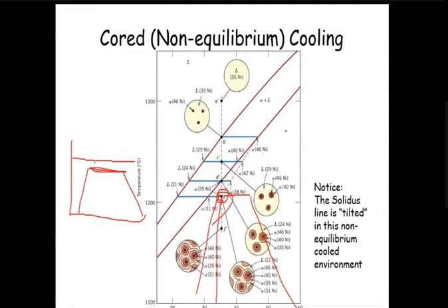So why is this holding important? Because due to this holding, all these solid phases, with composition ranging from 46 to 31, will start distributing their atoms. Diffusion of solid atoms will start, and due to this diffusion, a homogeneous solid phase will be obtained.